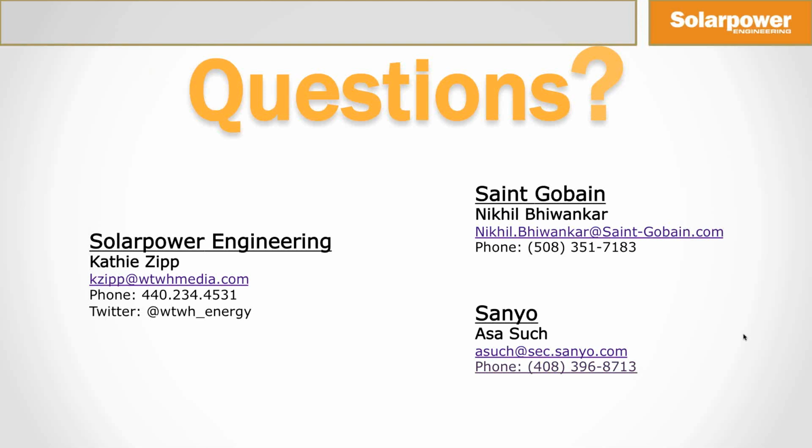Well, I'll just take that on behalf of all crystalline. Certainly there are crystalline solar panels that are old out in the field, and they're still continuing to work. The data is very thin on the ground. The average degradation from all manufacturers really is 0.5% a year, so most warranties will warrant 90% of day one power through the first 10 years, and then 80% of the day one power through 20 and sometimes 25 years.